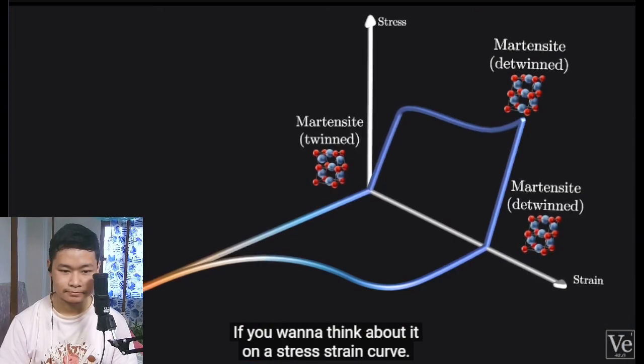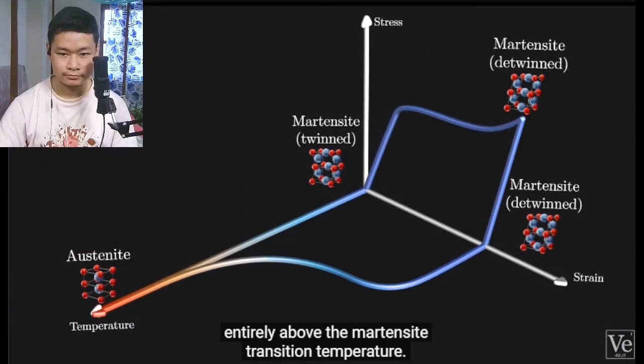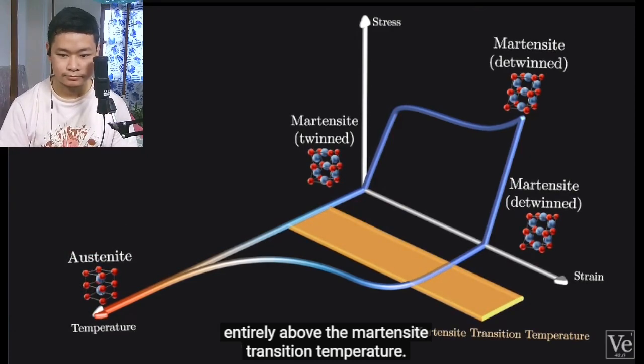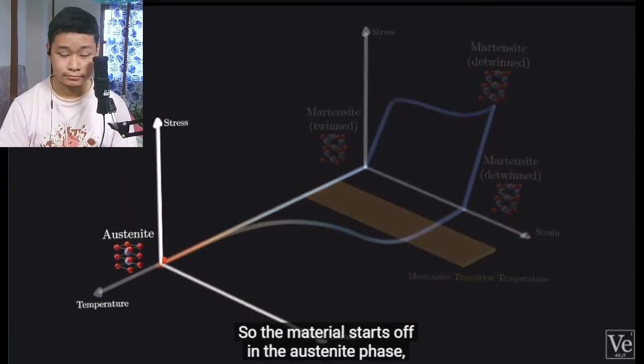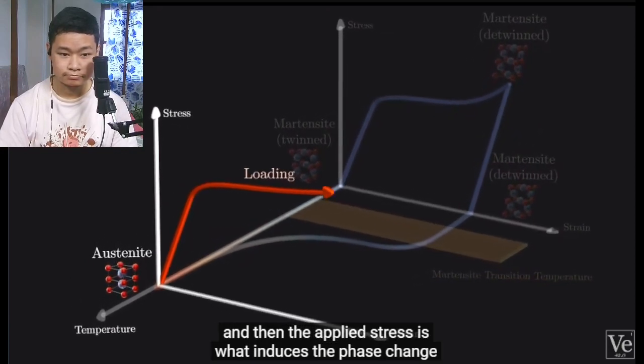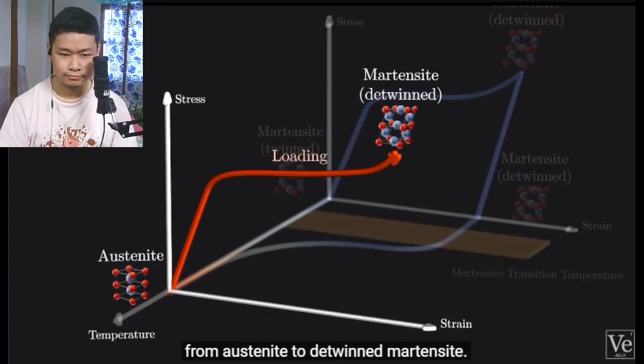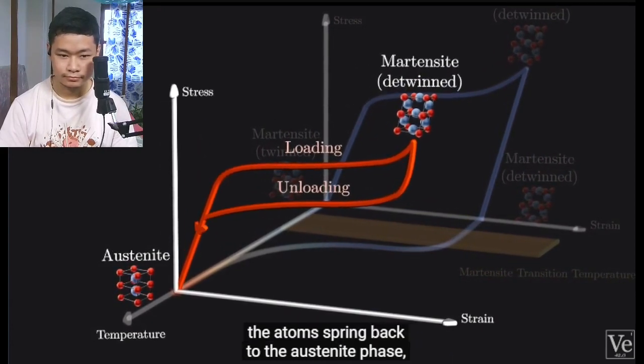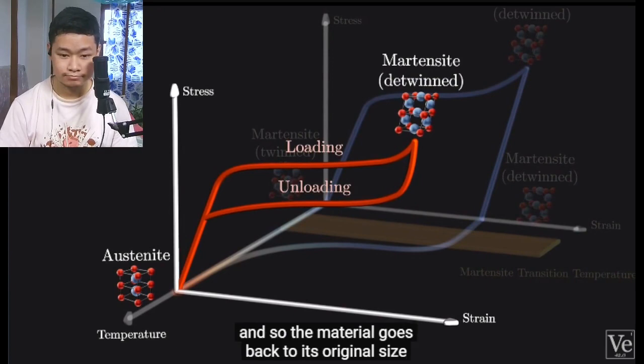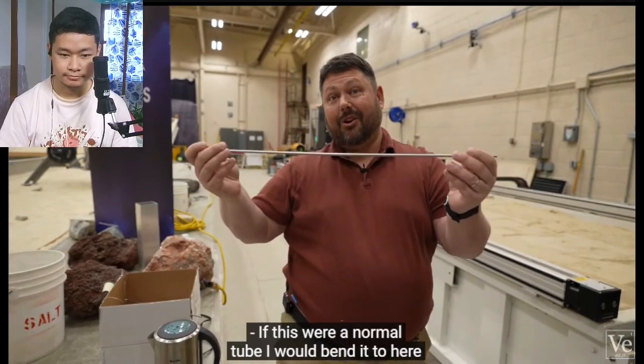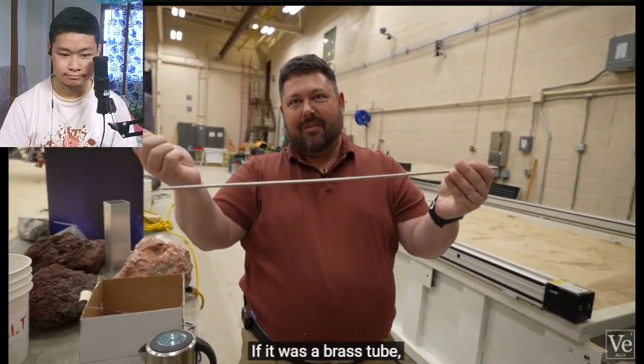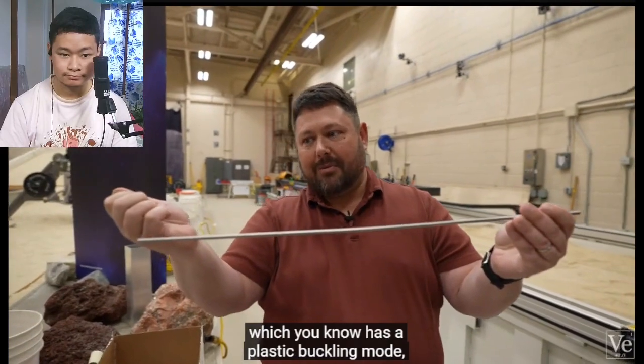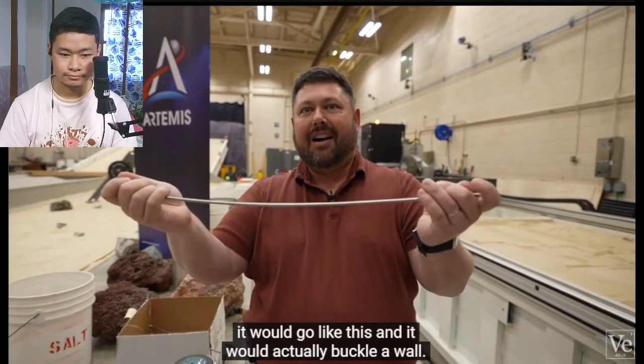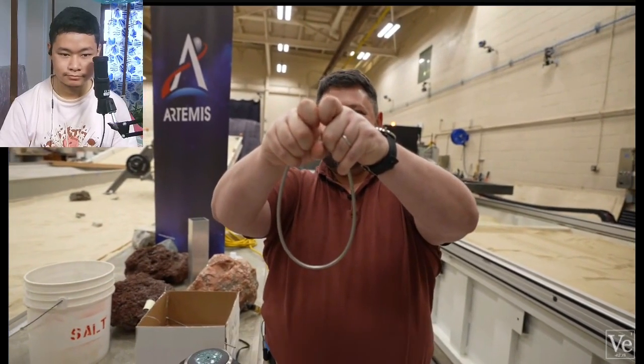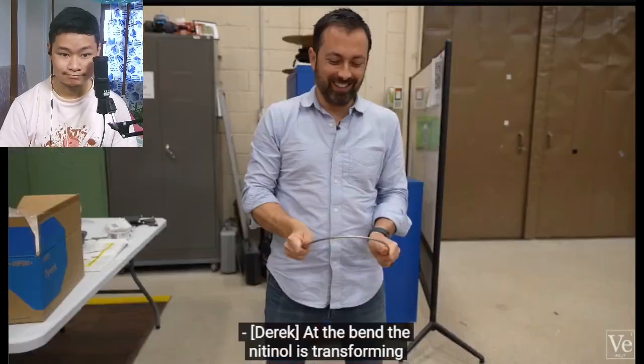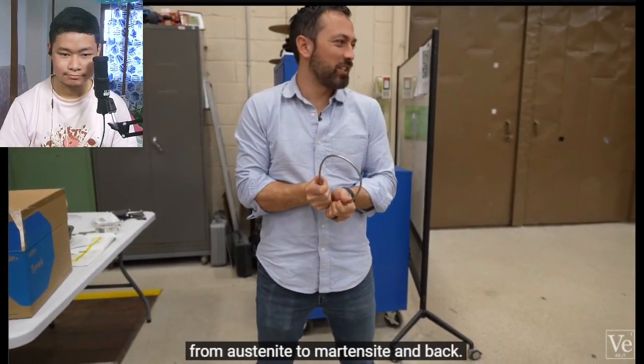If you want to think about it on a stress-strain curve, this transformation is occurring entirely above the martensite transition temperature. So the material starts off in the austenite phase, and then the applied stress is what induces the phase change from austenite to detwinned martensite. And when that stress is removed, the atoms spring back to the austenite phase, and so the material goes back to its original size and shape. If this were a normal tube, I would bend it to here and it would plasticize. If it was a brass tube, which has a plastic buckling mode, it would actually buckle the wall. I would never take my hands and bend them like this and have it completely return to shape. At the bend, the nitinol is transforming from austenite to martensite and back.